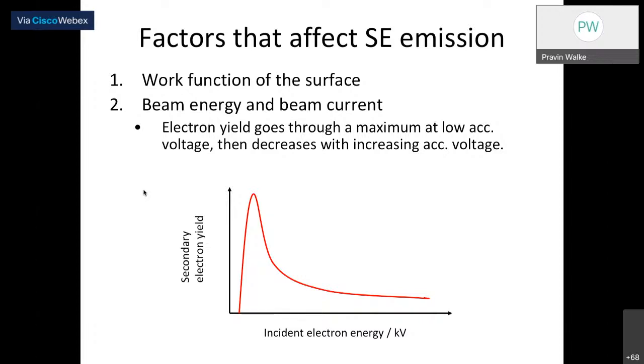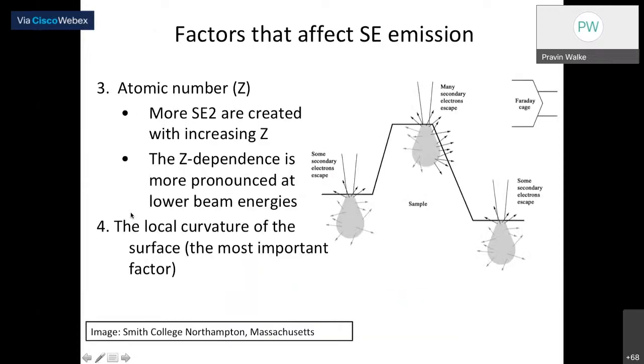Therefore, if you want a very good topographic image from the SEM, usually we need a very low accelerating voltage, right? There is a probability to get very high secondary electrons, and therefore you can get a very good topographic image by using this low accelerating voltage. Further important factors, as we have already discussed before, are atomic numbers. If you increase the atomic number, more secondary electrons are generated, right? There are several interactions inside the atoms, and then you find this secondary electron 2. This atomic number effect is more pronounced at low beam energies, right? So if your beam energy is very low, then this Z plays a significant role, right?